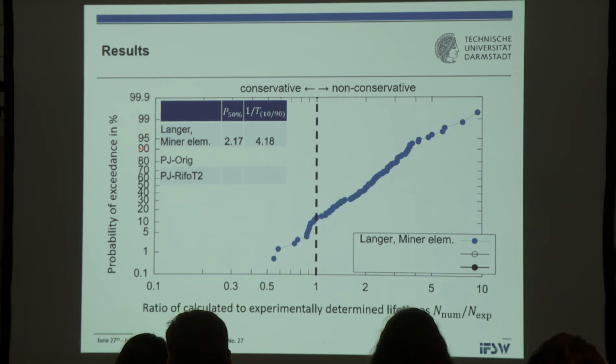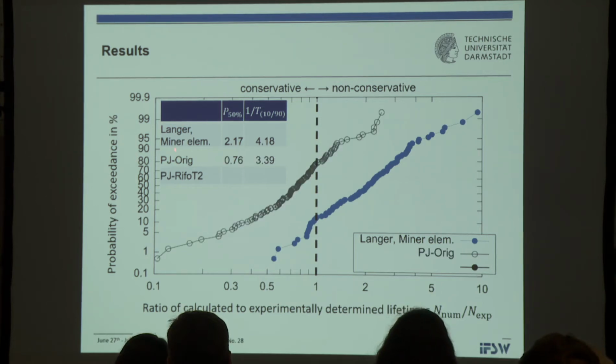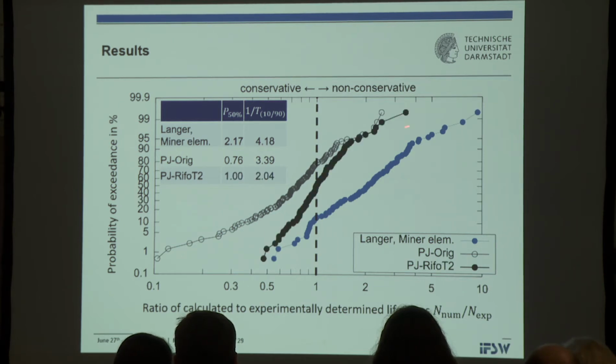It's simply go into this cumulative distribution here at the value of 90% of exceedance, take out the abscissa, and go in at 10% and divide these two values. And if this value is high, it's bad, and if it's 1, it's perfect. So PJ original, this is what I explained at the beginning of my talk, which is, by the way, now we have a guideline in Germany for mechanical engineers performing assessment of strength, the FKM guideline. Some of you might have heard about that. And this is now part of this FKM guideline, and these two results have been expected. We know that this PJ modeling is conservative and reduces scatter a bit. And our new approach, the results are here in these full black circles.